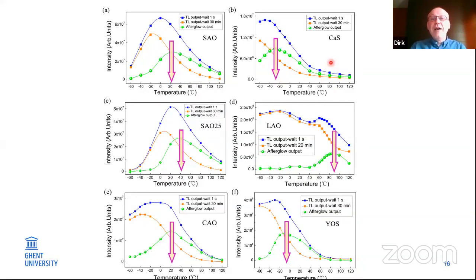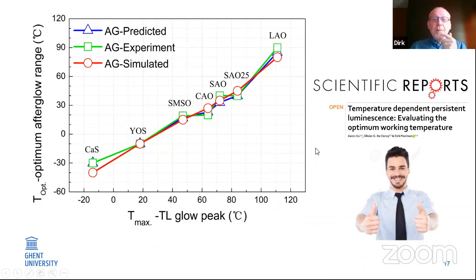For calcium sulfide with europium, this is a negative temperature. So here the optimum temperature is far below room temperature. For lanthanum aluminate, the example I showed on the previous slide, it's way higher than room temperature, at around 90 degrees centigrade. So what is the main conclusion is that different persistent phosphors behave differently at different temperatures because the trap depth is different for these different compounds.